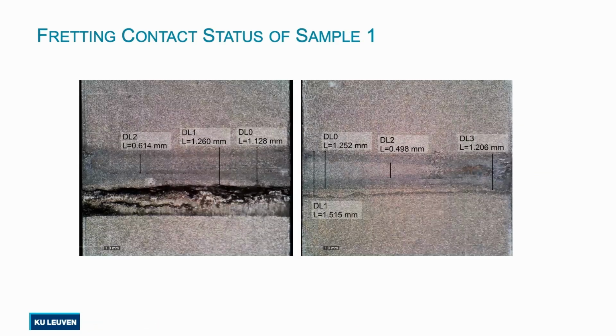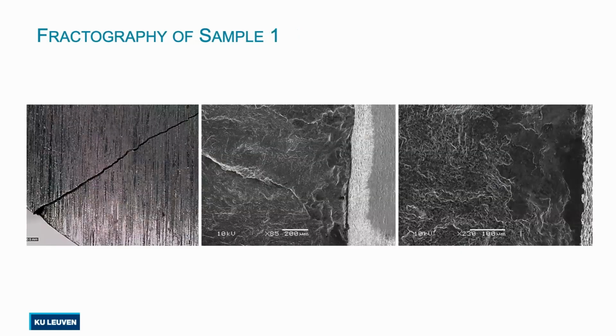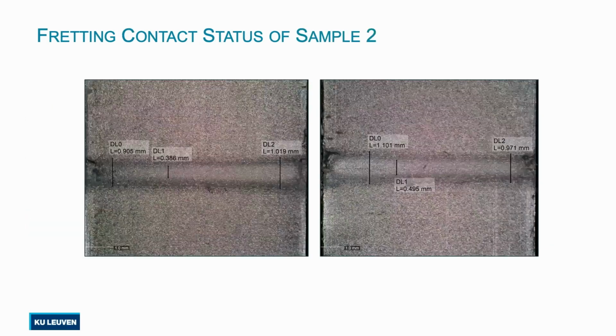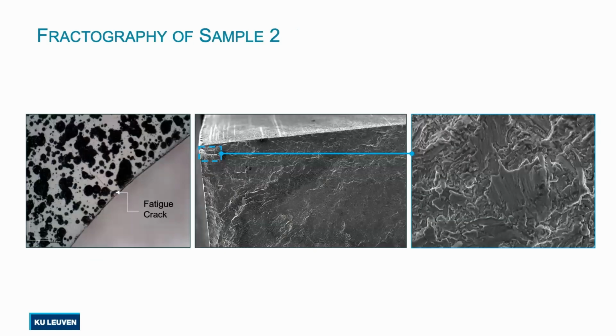The first one was fretting fatigue. So here you see the contact interface, sticking area in the middle and slipping area at the edges. If you look at the micrographs, we see that the crack initiated at the surface. The microscopy is also confirming the same. For the samples which did not fail at the contact interface, we have this distinguished slipping situation, but we saw that the crack initiated at the edge, and we found some kind of defect probably induced by the AM manufacturing process, but it's more sensitive than the wrought material.